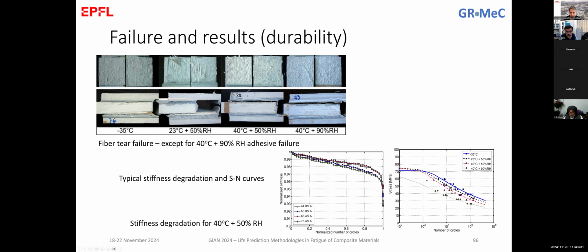In the first case, we had a cohesive failure, which means that the crack was initiated randomly, but then it was always switching to the first layer. If you see here, the failure is always in the layer of the adhesive. It's not in the composite, and it's not in the interface, except for the case where we had a lot of water, this 40 degrees and 90% relative humidity, where we had an adhesive failure. So this humidity, this water, led to adhesive debonding. The adhesive failure means between the adhesive and the composite.